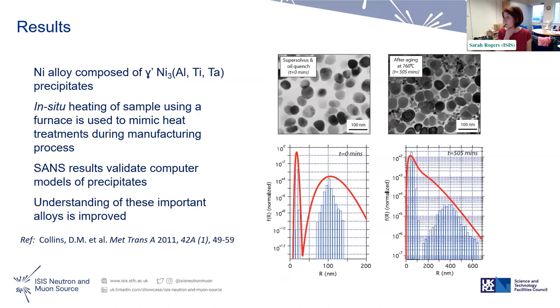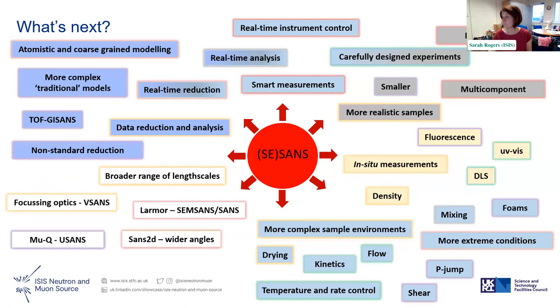So the results: we could clearly see that these nickel alloys were composed of these different precipitates, which is really great. We did lots of in situ heating of the samples using a furnace to mimic these heat treatments that they do in the manufacturing process. And then they also did electron microscopy. We like to do different measurements to really get a full picture of what's going on. And the SESANS validated the computer models that they had been using. So it gave them a really improved understanding of these important alloys and how to develop them further.